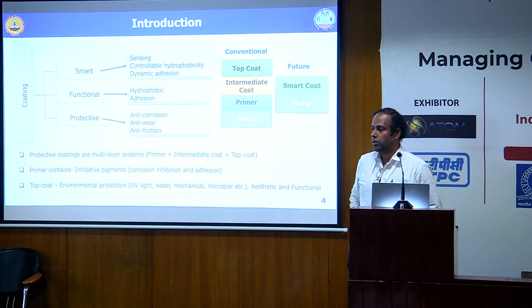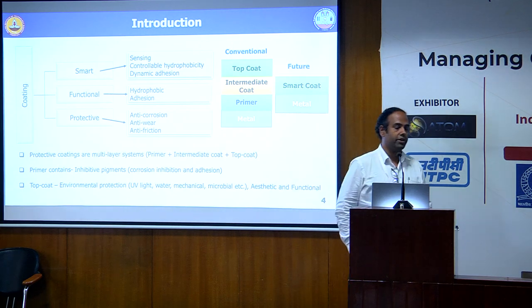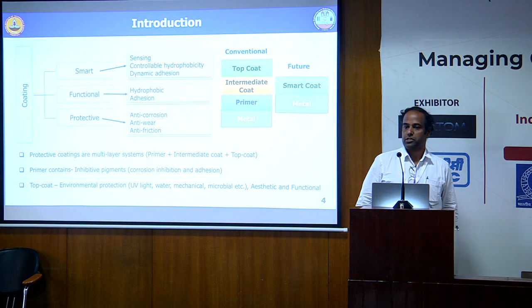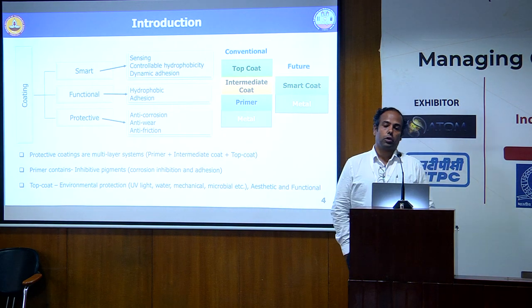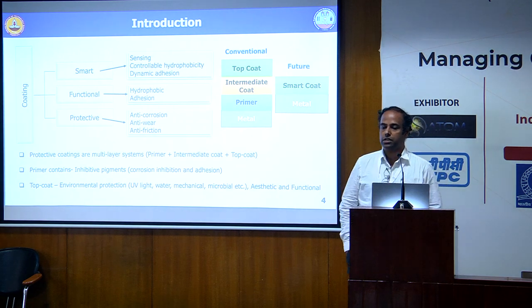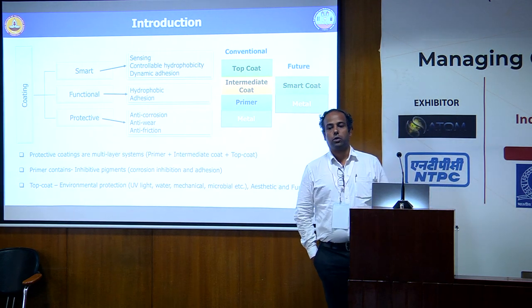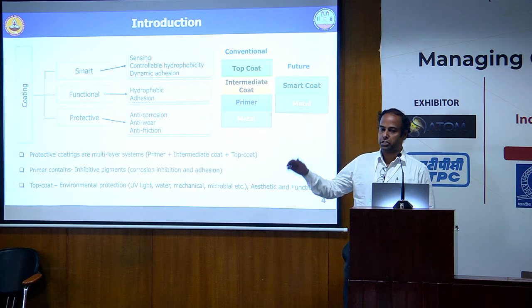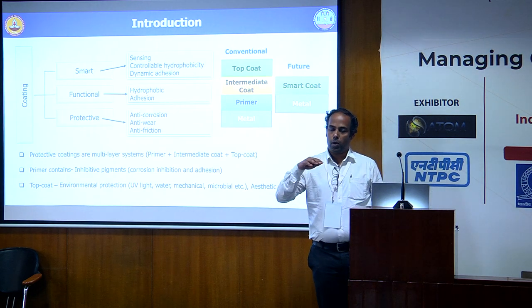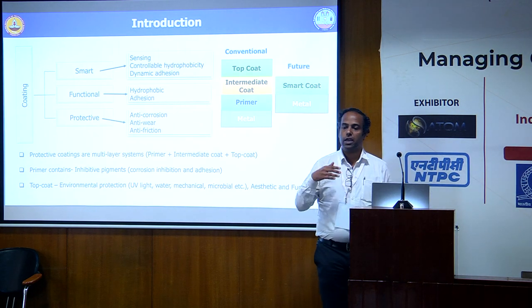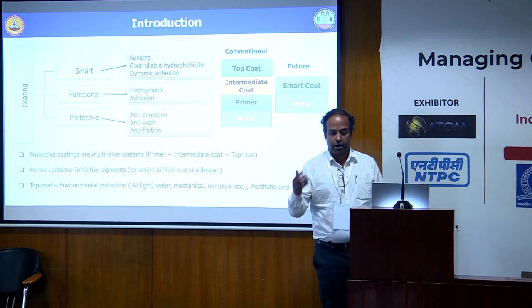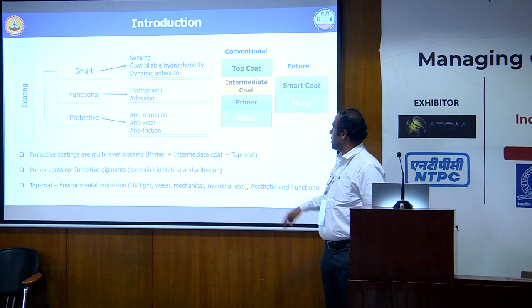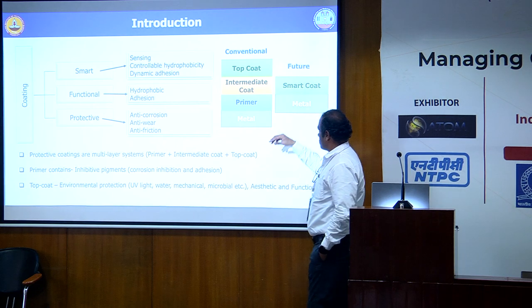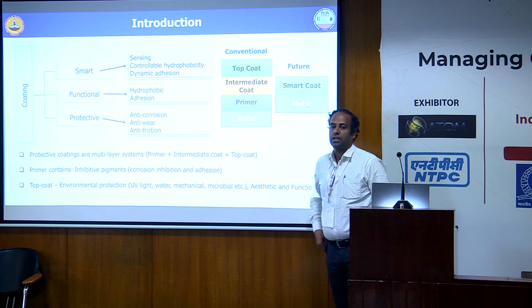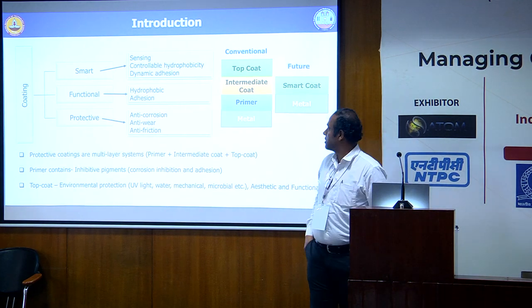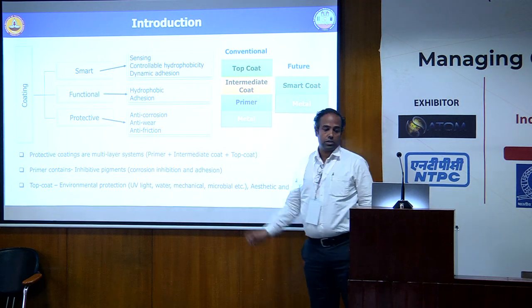Today, I'm designing my talk on a particular aspect of corrosion where we try to develop a smart composite coating. We all are aware of corrosion prevention methods, and one such method is coating. A typical conventional coating has multiple layers with multiple functions. You have zinc primers, then the top coat which should resist UV, it should resist wear, etc., and it should be hydrophobic. But today, we replace this multi-layer, multi-stack coating with a simple one, which is called a smart coating. It should have what is in the primer, intermediate, as well as the top coat.